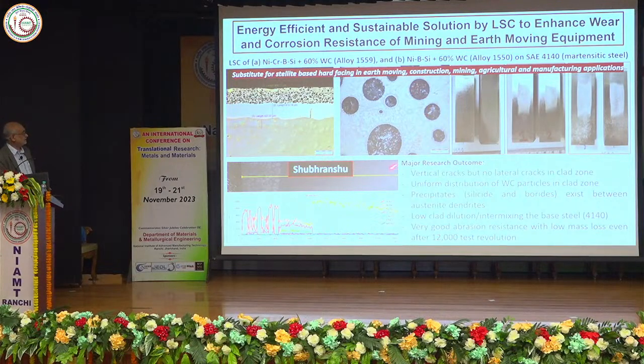And then finally, for earth moving equipment, Shubhranshu wants to develop a similar thing, but with something new — he wants to not only use one of these high alloy steel clads, but also disperse tungsten carbide into them. Now this is different from the stellite kind of cobalt-based tungsten carbide dispersion in terms of coherence or compatibility, and you get very nice spherical objects.